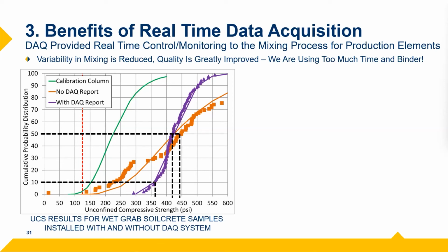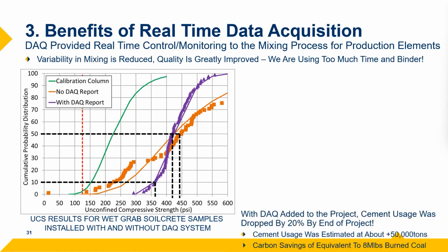So this is the specification that we're trying to meet. 90% of our samples have to be 125 or higher. Here, we're at 360. Well, what does that tell me? Based on how we were doing things previously, where we were using kind of visual cues and this lag in strength testing, we're using way too much cement, okay? So the benefit of this data acquisition system, not only is that it gives us this better quality, but it's really going to allow us to start using less and less material and improve our costs and time.